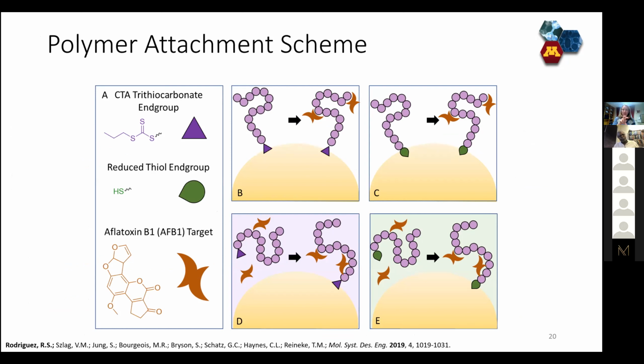That's the piece that came from the charge transfer agent that I showed you. And when there's a green teardrop on the end, that means we've converted the trithiocarbonate to a thiol, and I'll explain that in a second. And then if you compare B and D to C and E, the main difference is whether we attach the polymer to the surface and then flow over the aflatoxin, or whether we let the polymer and aflatoxin interact first and then introduce it to the substrate.